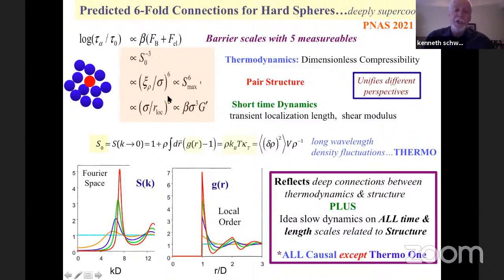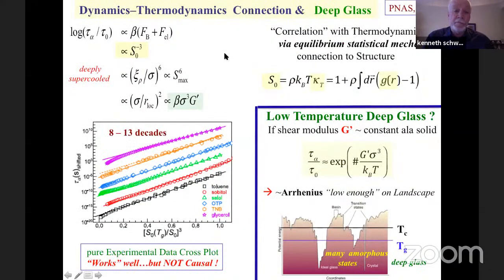Now, all these predictions are causal. That is, they're directly related to the core ideas of the theory, with one exception, the connection to thermodynamics. The theory is not relating thermodynamics directly to dynamics. However, you can test it. Because the theory predicts the log of the relaxation time scales inversely with the dimensionless compressibility, you simply go to the literature, and it's in this recent paper. You look up the relaxation time of many systems. Here's 6 of them, 6 molecules.